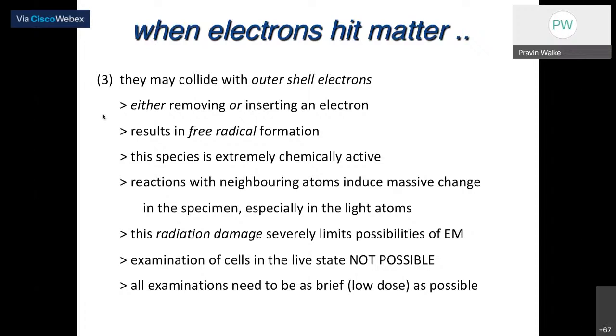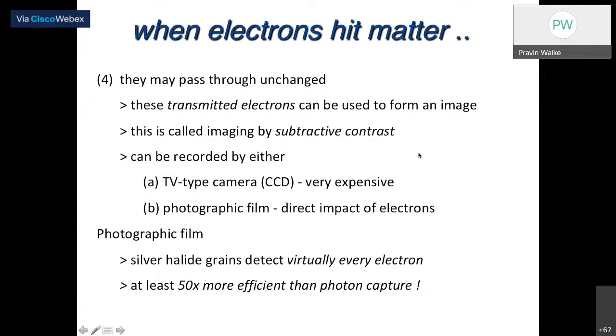So for all these examinations, probably with a low dose, people can try out, but this low dose may or may not work in this case. So the fourth one: what happens if your electron doesn't interact or collide with your specimen, and it will be unchanged and transmitted electrons, which can be used for this kind of imaging in TEM, right? And this is usually called subtractive contrast, right? So subtractive contrast, because there is no interaction of your beam with the specimen, just transfer,